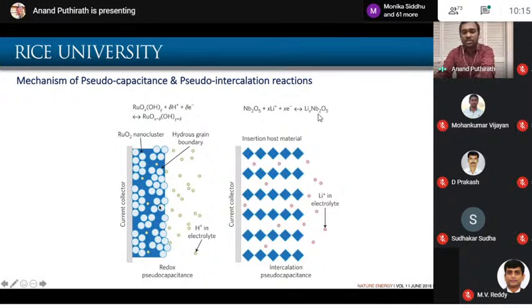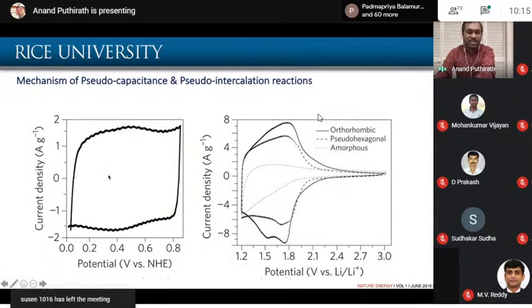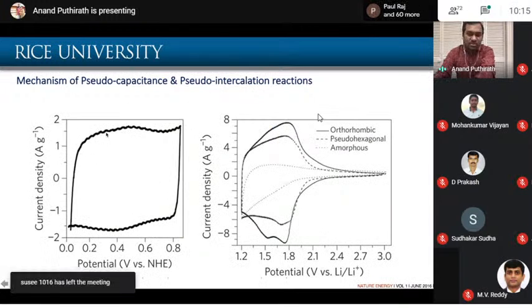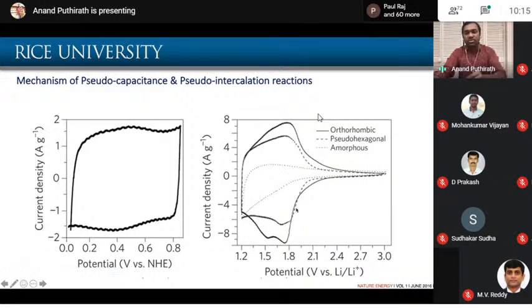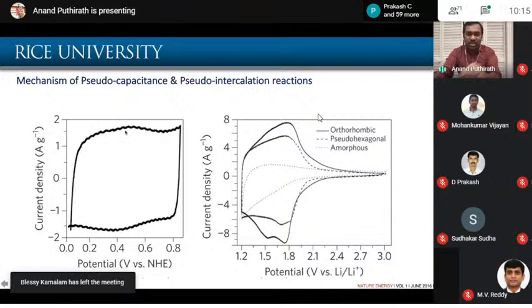Capacitance comes out, or charge storage comes out, and there are some other materials where atoms will intercalate into the system. That is slightly battery-like and still fast enough. Some structures will allow fast kinetics. And if you see the CV, this is the pseudo capacitance on ruthenium oxide, and this is the intercalation-based capacitance. You will see a well-resolved cyclic voltammetry oxidation reduction curve for intercalation, and for partial oxidation reduction, you will see these small features.